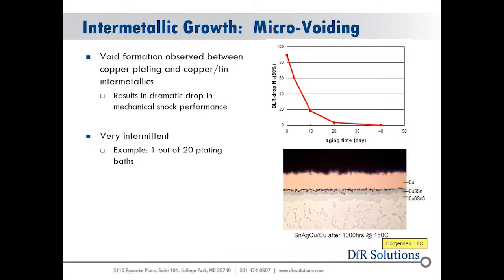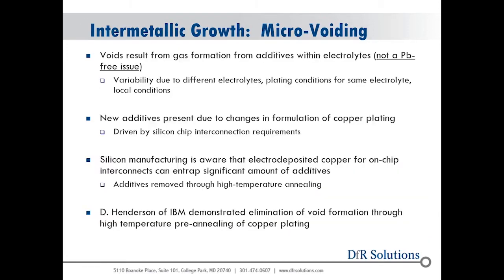Another issue that can reduce strength during shock, Kirkendall voiding or microvoiding. Kirkendall voiding is due to excessive intermetallic growth. This type of microvoiding is more of an effect of organic contaminants in the copper plating solution. And so they pretty much figured out how to get rid of that. Not something we have seen recently,